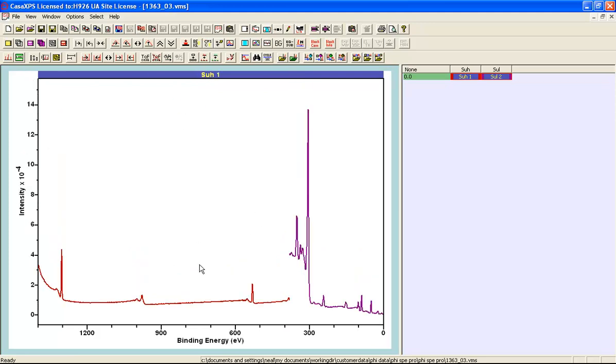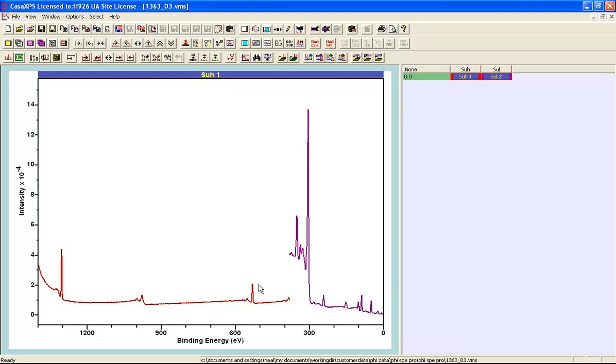We can see here that one of the objectives of this measurement was to ensure that the oxygen 1s peak has been measured with the same intensity in terms of counts per bin as the magnesium 2s and magnesium 2p. The reason this is important is because the uncertainty in the data is proportional to the square root of the counts per bin.